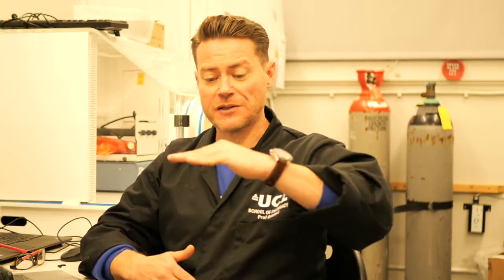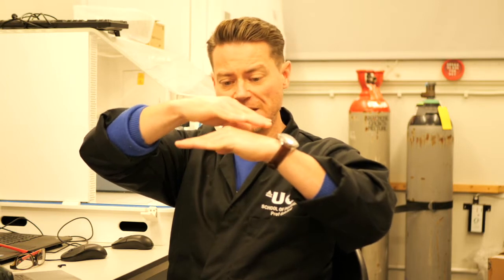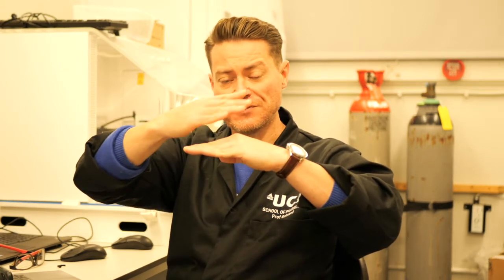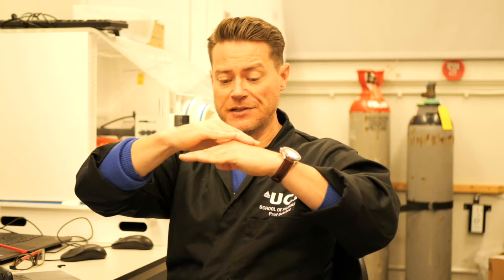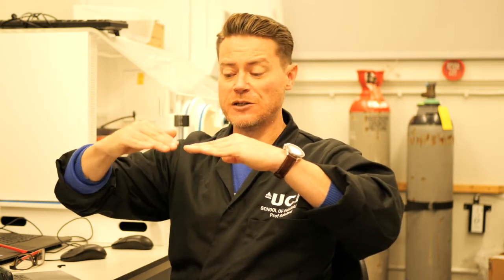Then what you do is you take your sample, which is pretty small, it's got to be said, normally maybe 100 microns by 100 microns. You bring your tip down onto the surface of the material and you raster across the surface of the material, same as in SEM. So you go in one direction, measuring the Z deflection, then you move over and go across the surface again, measuring the Z deflection. So you should end up with an image which is X, Y, Z. Okay, so it's a topographical image of the surface of your material.